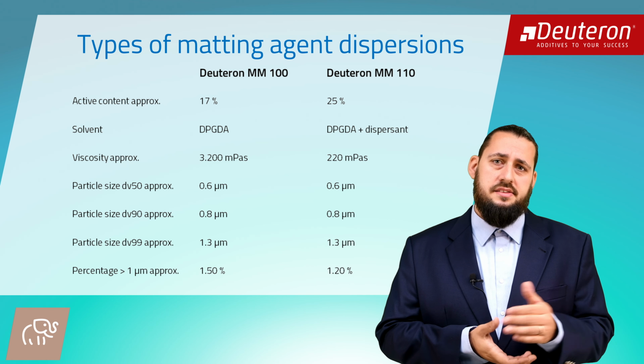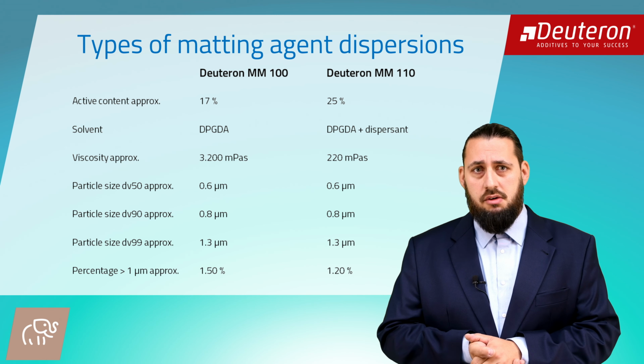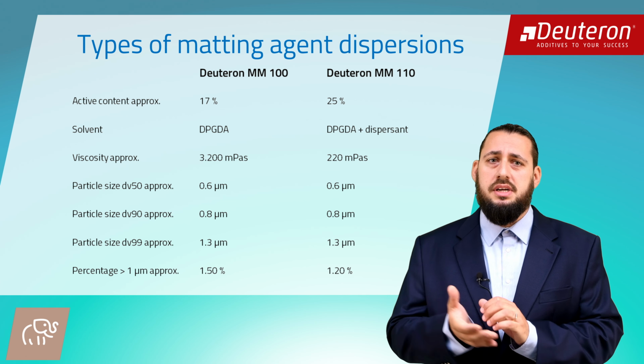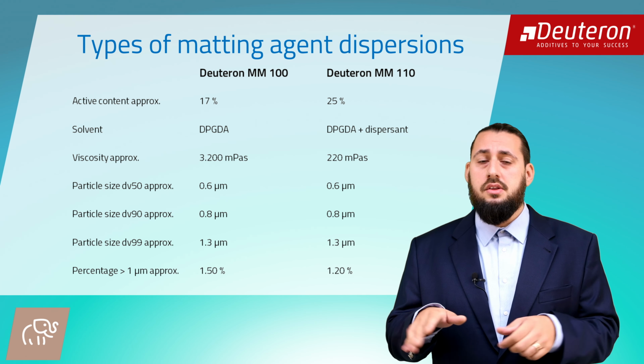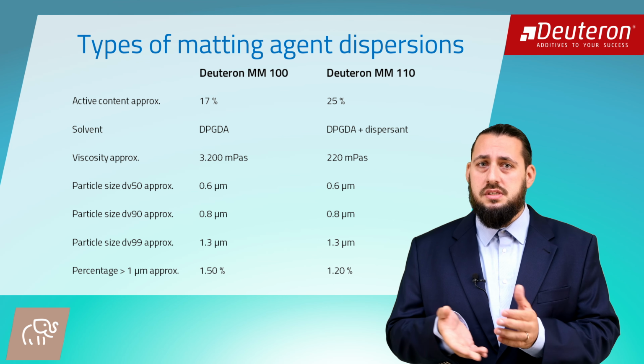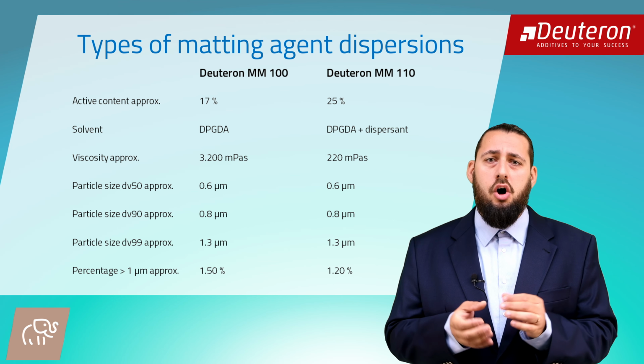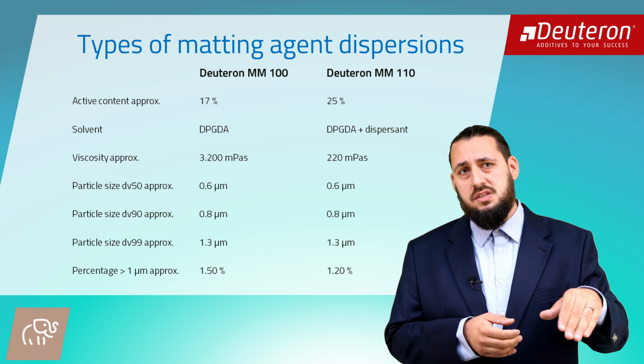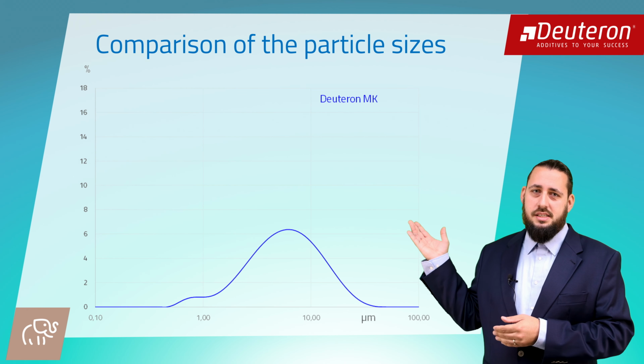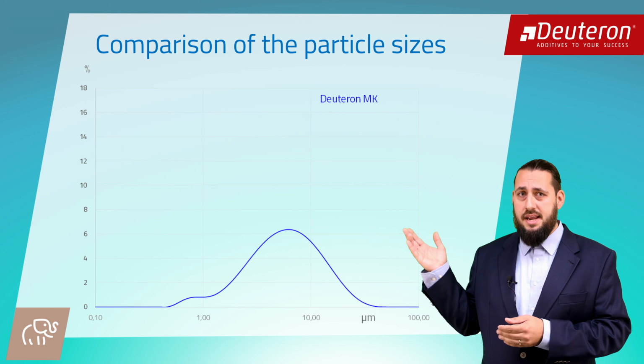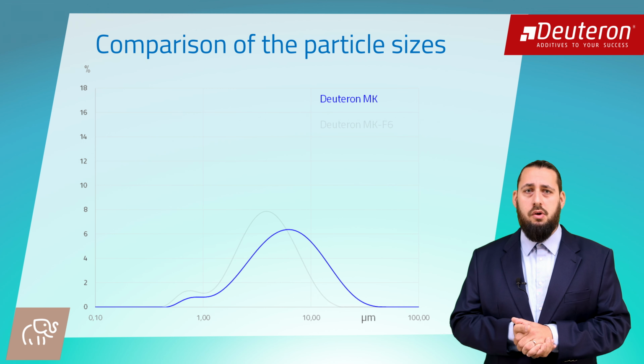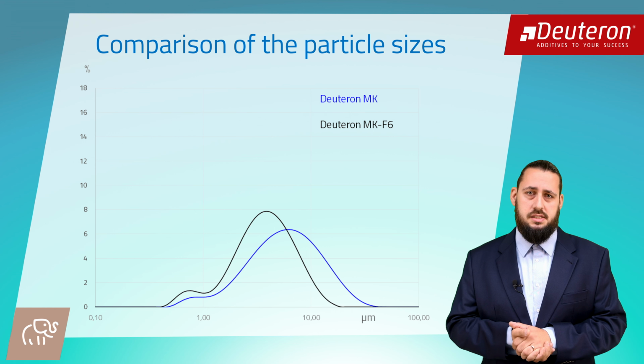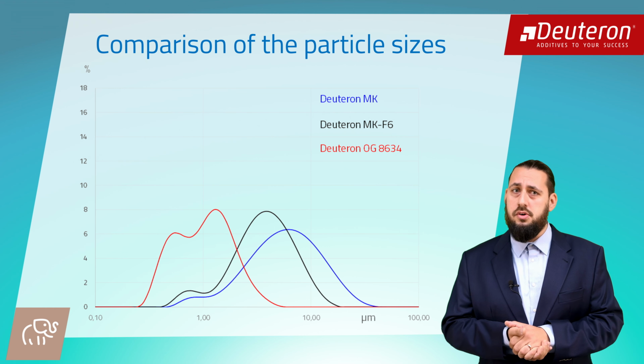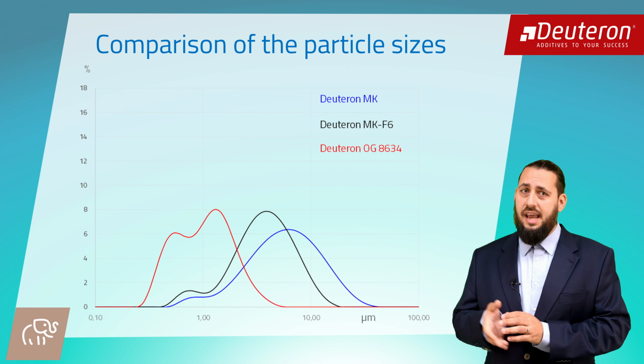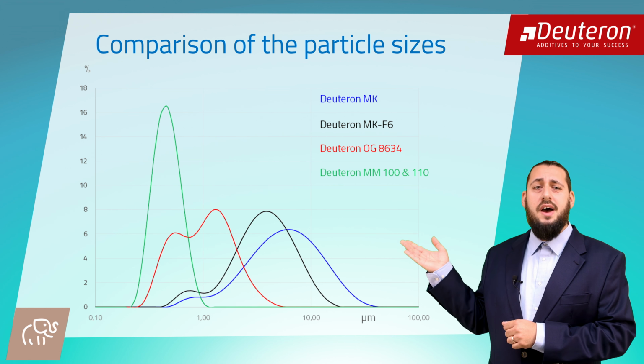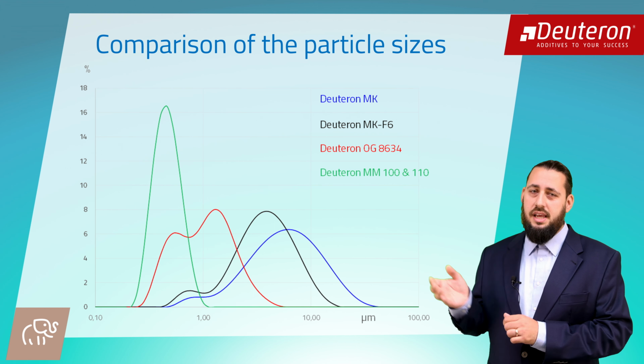Deuteron MM100 has an active content of 17% with a comparatively high viscosity, but is completely free of additives. Deuteron MM110 uses a dispersion to achieve a higher concentration of 25% and a very low viscosity. This is the particle size distribution of our standard matting powder Deuteron MK, followed by the finest powder grade Deuteron MKF6, and the finest dispersion of the Deuteron OG product range. And now the particle curve of the very fine Deuteron MM100 and 110.